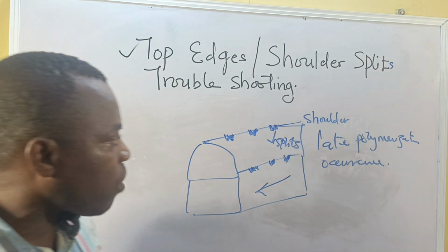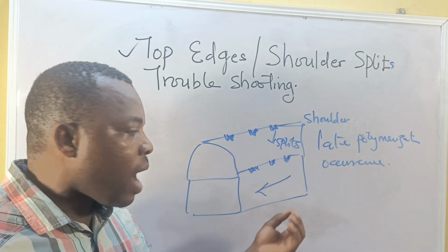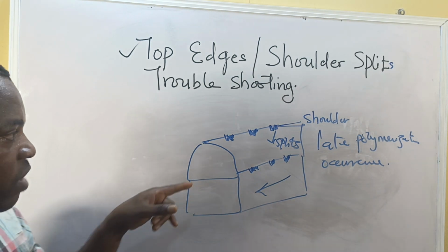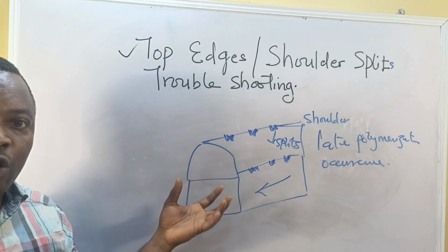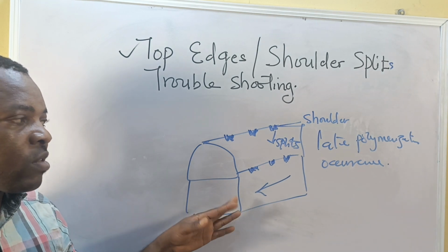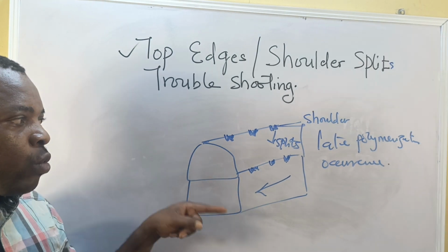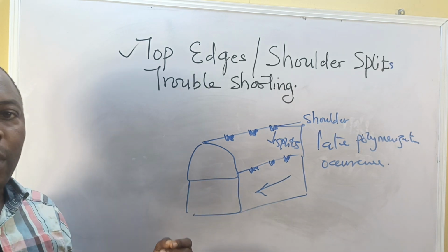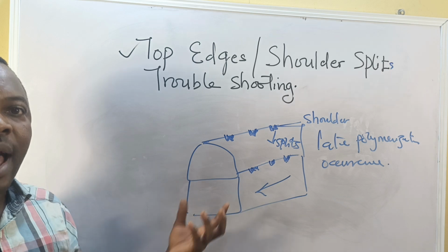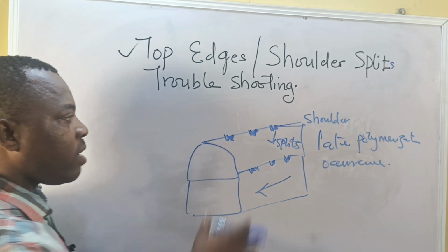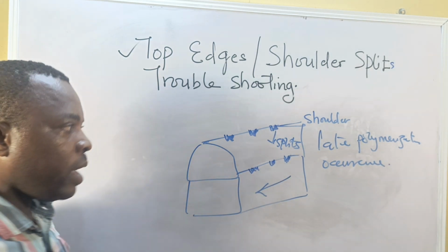There are several factors that could lead to this: the temperature and the use of your tin catalyst in that reaction. The tin catalyst here may not be sufficient. It could be sufficient, but because the temperature is a bit cooler, it will counteract the strength of that particular formulation you were using, making it seem insufficient as a result of temperature. So it will make this polymerization occur late.